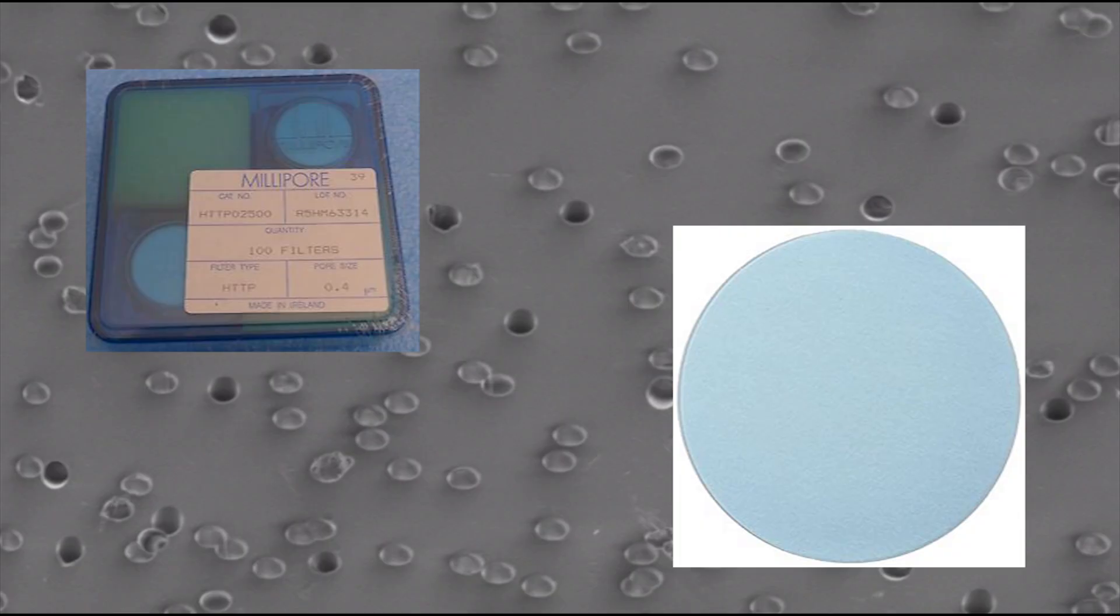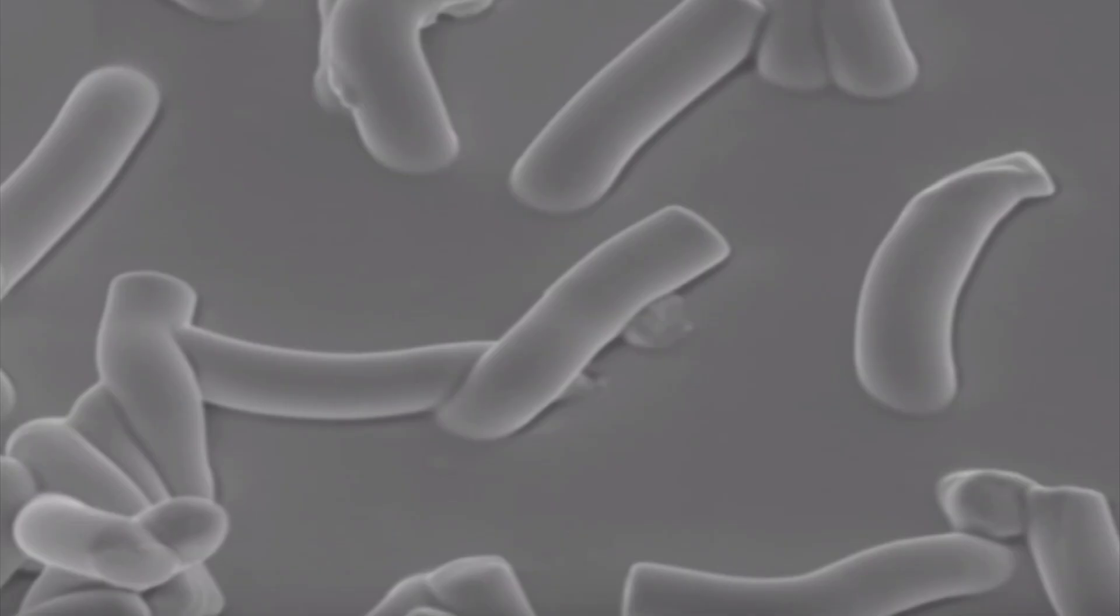rely on casting the silicone on special micron pore filters. The idea being that the silicone will flood the tube of the pore and then cure so that when you pull the two apart, you get a sheet covered in tiny hairs. But the issue was the hairs ended up being so floppy and at weird angles so it doesn't actually work. Also, they were way too sparse.